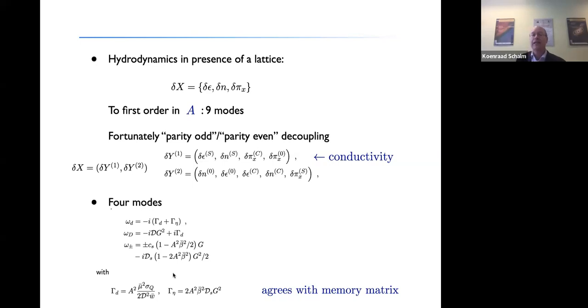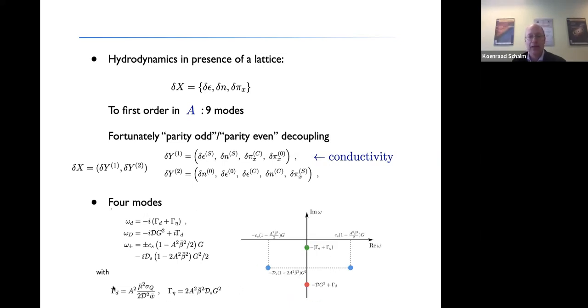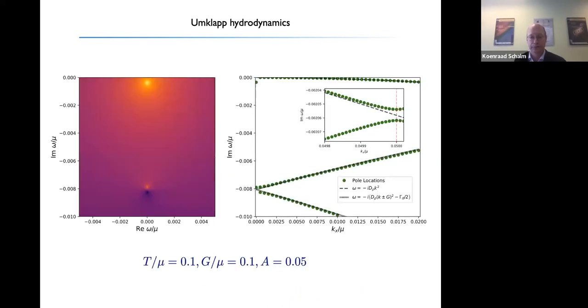Of course, studying hydrodynamics, or particularly transport in strongly coupled systems in the presence of a lattice, has been done before. You can do this in a memory matrix type method. In the memory matrix, you indeed find that the dominant contribution, that is this pole, has the same values as the memory matrix component. But what the hydrodynamics analysis gives you on top of the memory matrix is these other 3 modes and their contribution.